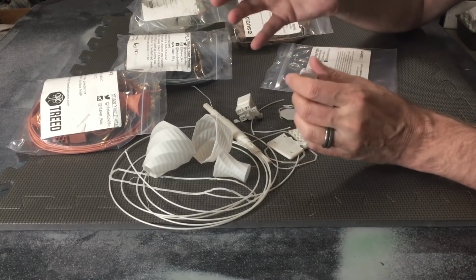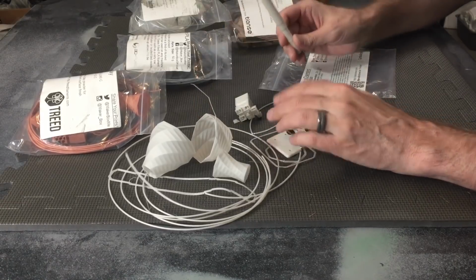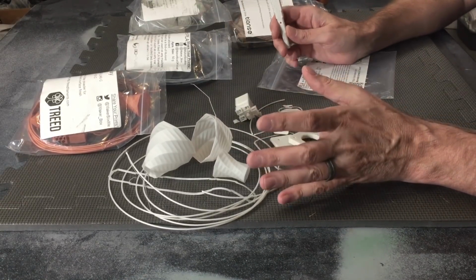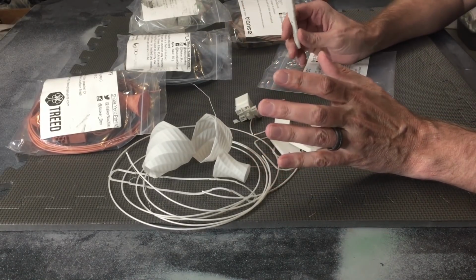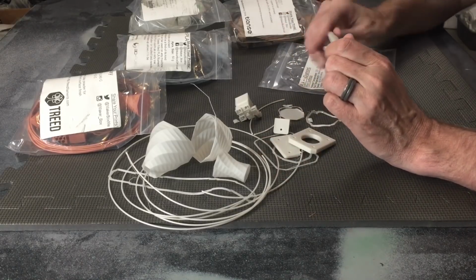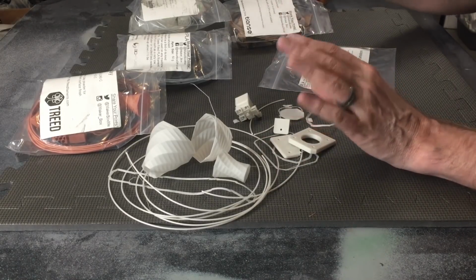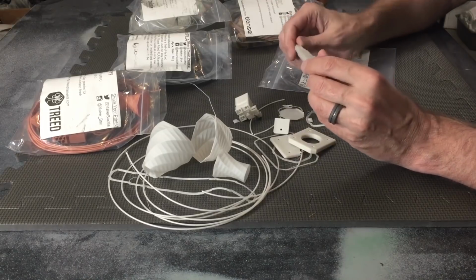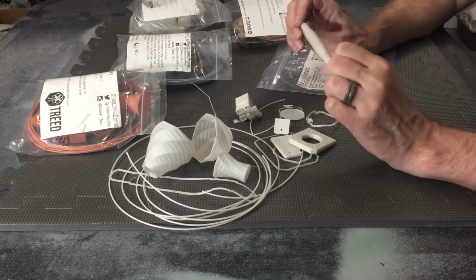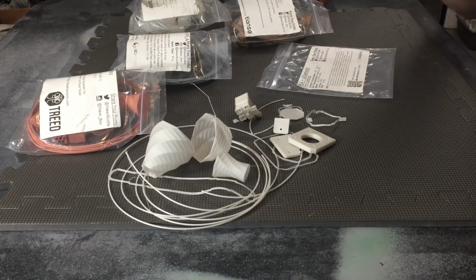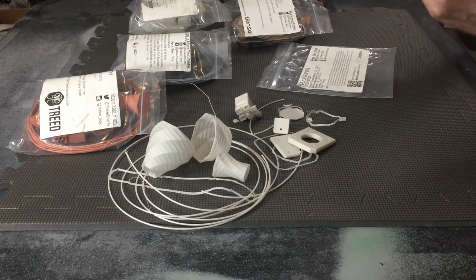So there is a give and take with this particular filament. If you want to utilize the strength, you have to print really hot. And I would suggest printing on a surface like a PEI or maybe a Gecko-Tech sheet, which a sample was included, which I did not get to test. Sorry about that. You would need a better print surface because this requires some special bed adhesion. I think those nanoparticles not only lubricate the filament, but they also lubricate that first layer and make it a little bit difficult to stick.